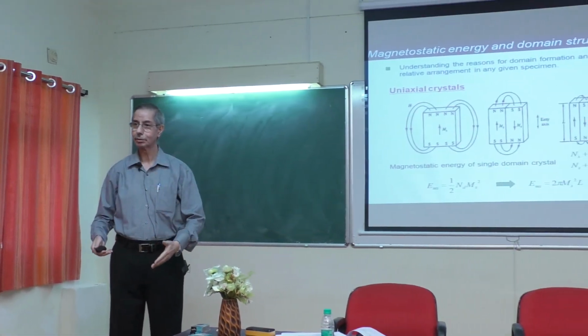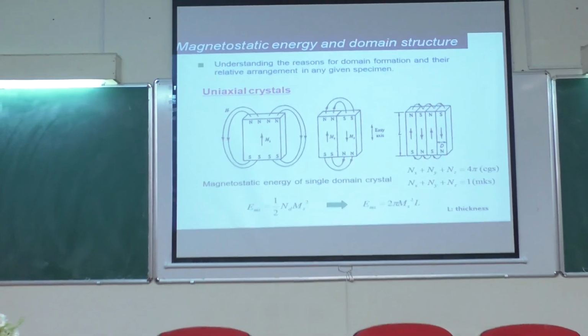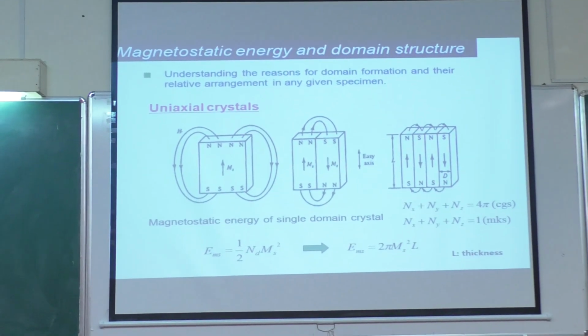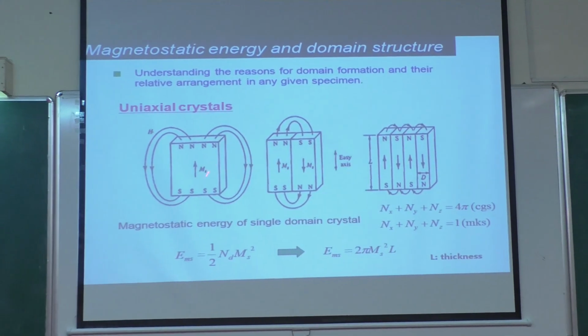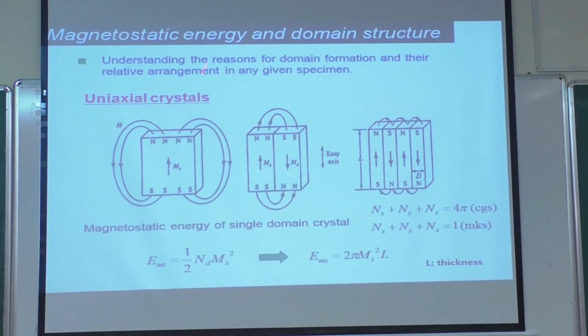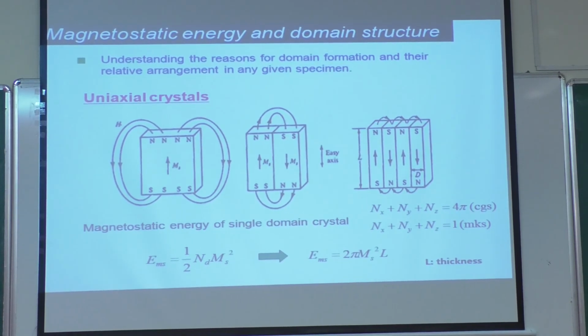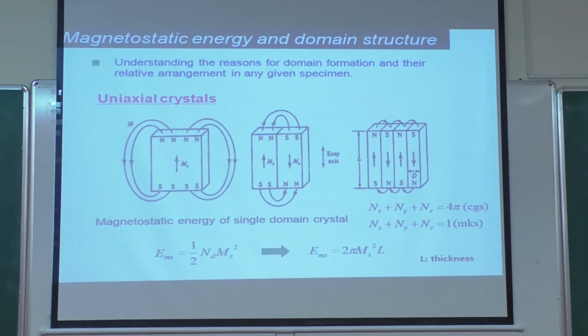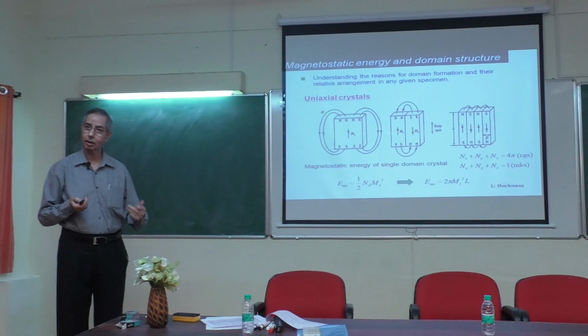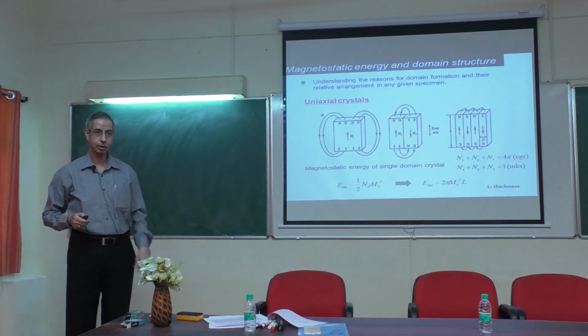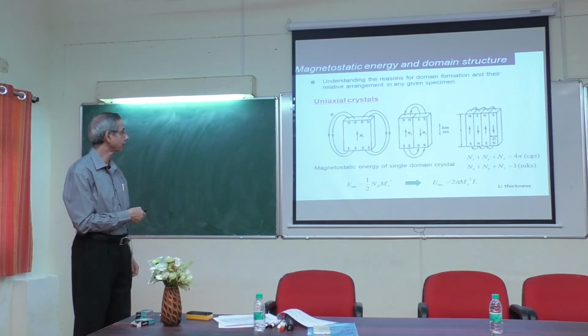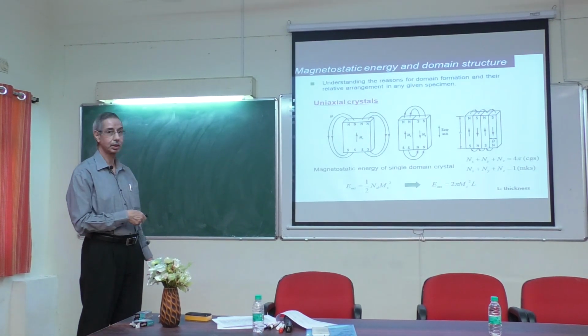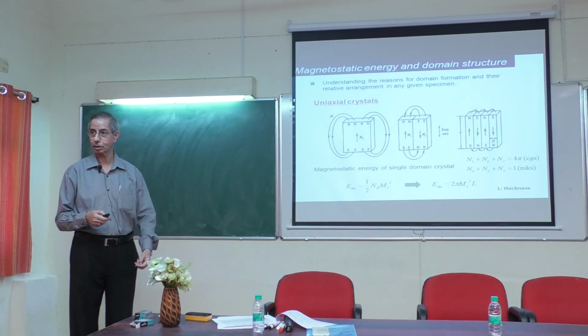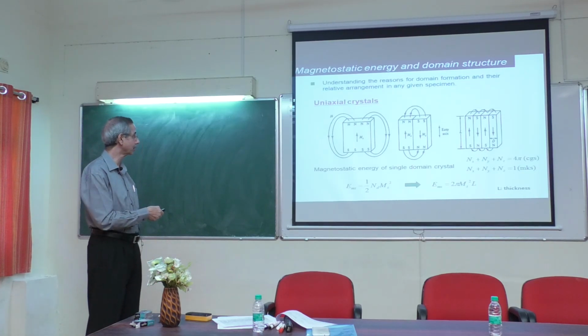Now let's say my single crystal is a single domain sample. Okay, so there is only one domain. Then I have all magnetization pointing like this within that whole sample. All the spins are going like that only, and in this configuration the exchange interaction energy is minimum because the spins are parallel to each other. When it comes to the anisotropy, this happens to be the easy direction of magnetization. So no problem, the anisotropy energy is also minimum in this configuration.